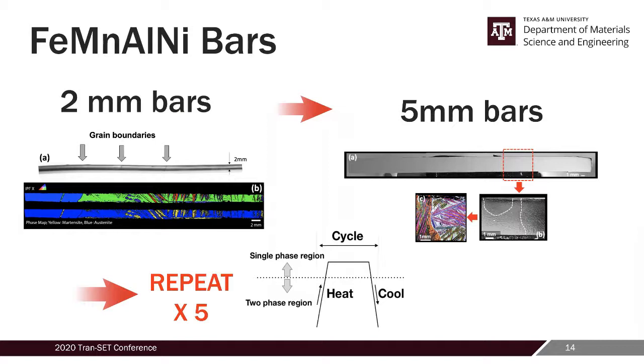After that, we worked on 2 millimeter diameter bars and 5 millimeter diameter bars. Again, we applied these abnormal grain growth heat treatments to these materials and repeated them 5 times from room temperature to 1200 degrees C, and we were able to grow the grains in these bars too. But again, this heat treatment is very important because you need to optimize the heat treatment specific to your material. As the dimension of the component increases, the heating and cooling parameters or the microstructure will change. Therefore, you need to optimize the heat treatments as you scale up the material.